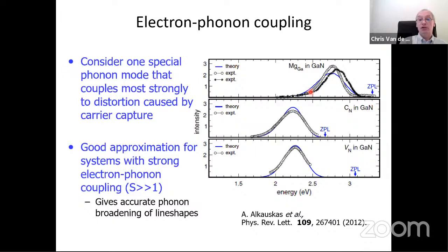Okay, so here are some examples of doing that for various defects in gallium nitride, and comparing theory, the solid curves, with these digitized curves for experimental measurements. You see that there is remarkably good agreement for most of these defects for the computationally predicted luminescence line shapes to agree with the experimental line shapes.